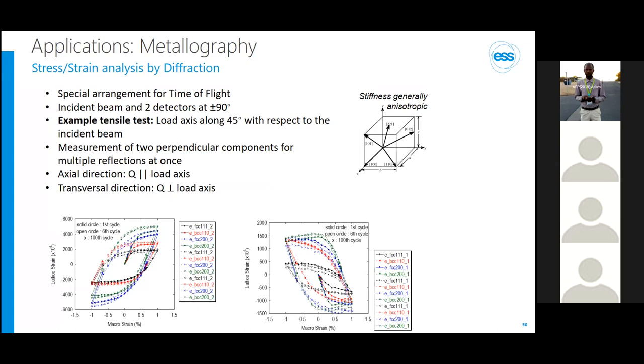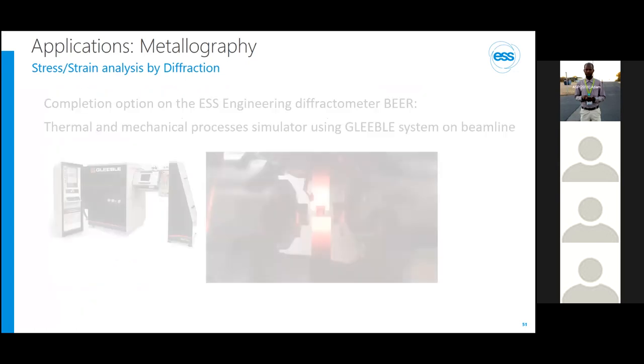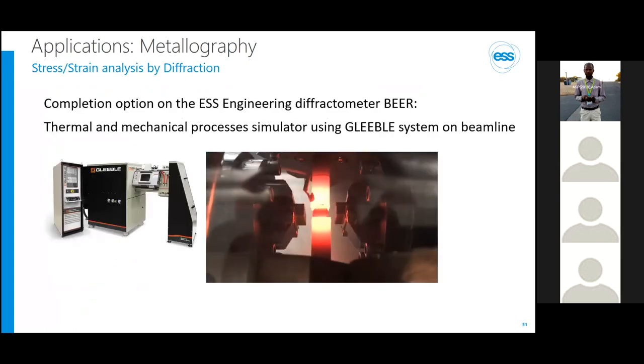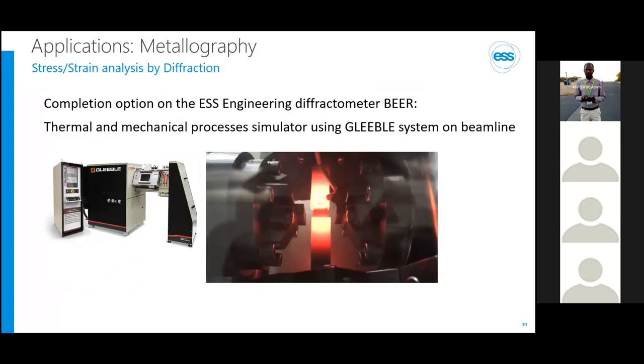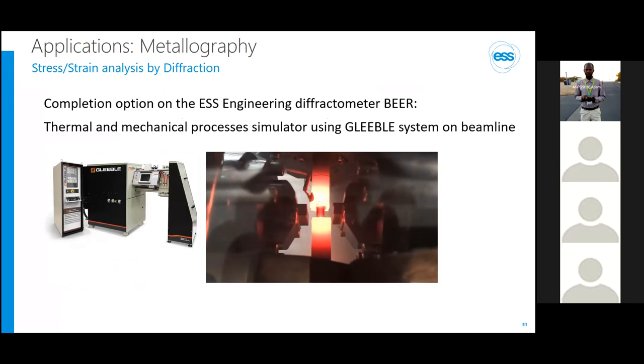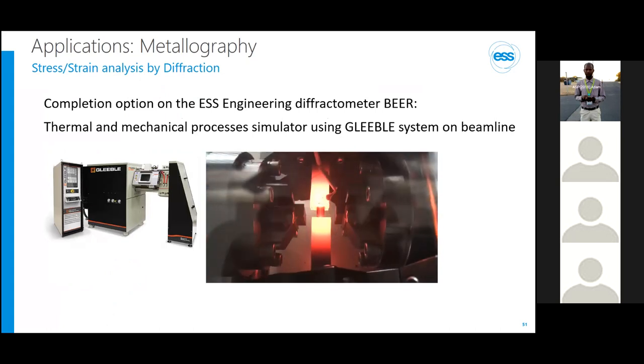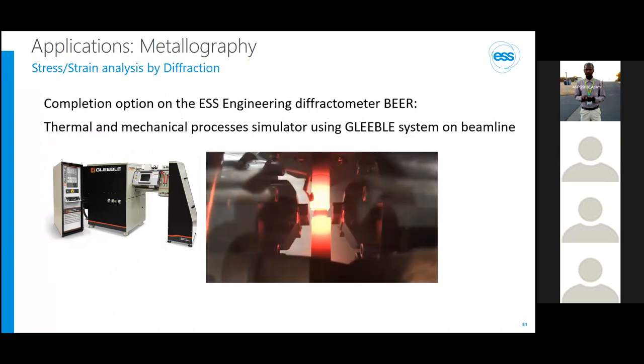If you have this kind of setup and you do loading and cyclic loading, you can, for example, study the internal residual strain buildup during the cyclic loading experiment, and you can extract vast amounts of information about your system. And as I said, since neutrons are so ideal for non-destructive testing of in situ processes, one can, for example, install a Gleeble on the beamline to simulate complex thermomechanical processes while doing the measurements, and what you see here.